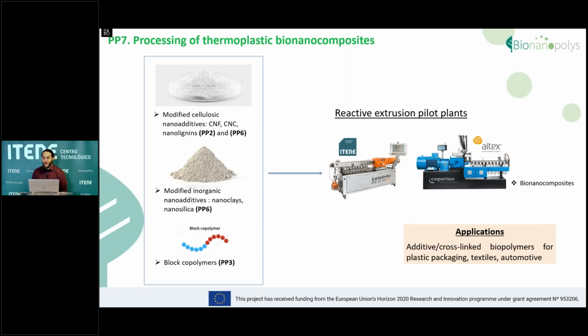As well, we can also do reactive extrusion with our pilot extruders by adding monomers that will react through the mixing process to allow a better mixing and integration into the polymer matrix. This could achieve thermosets and cross-linked biopolymers with improved durability.